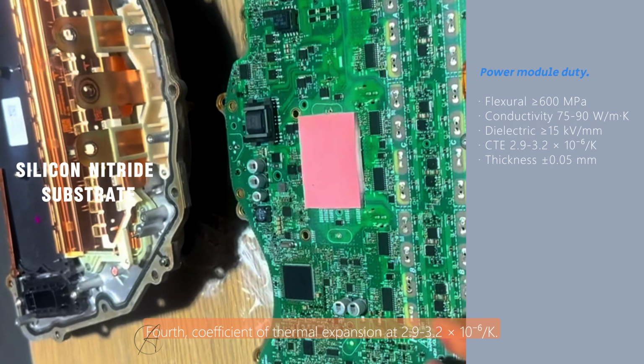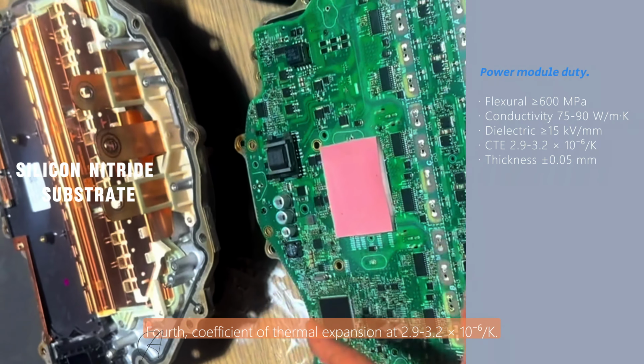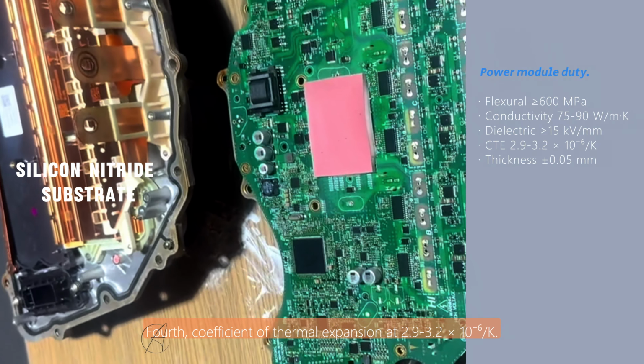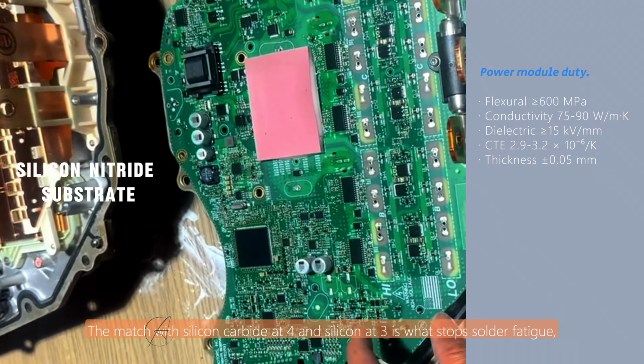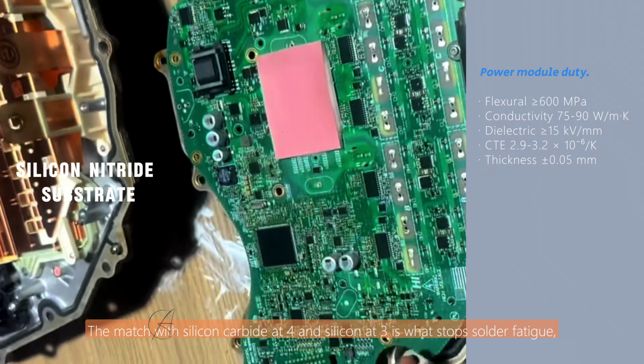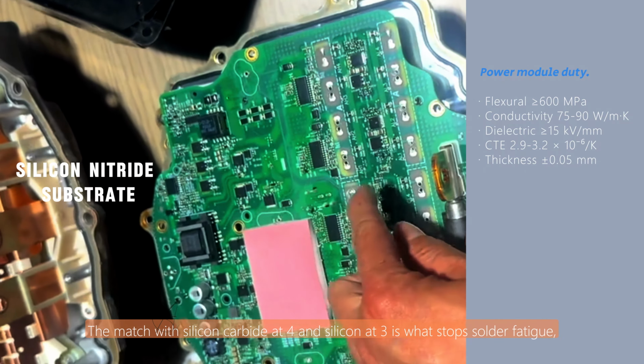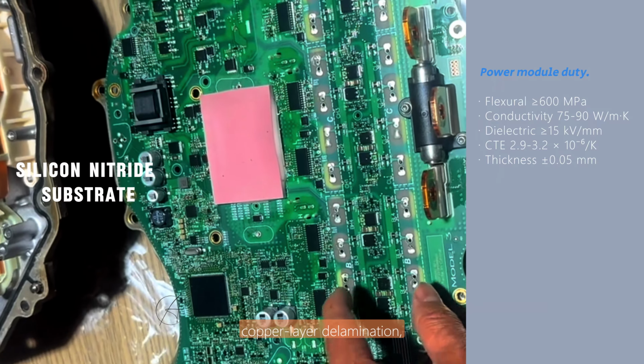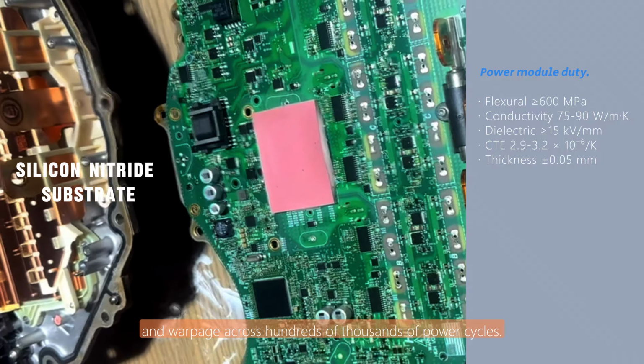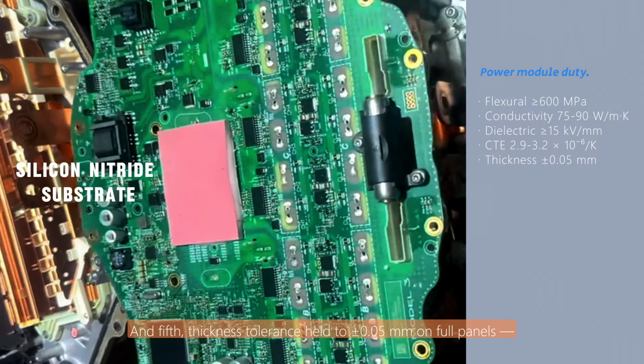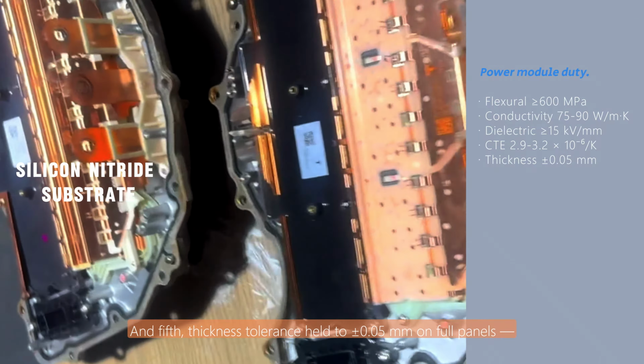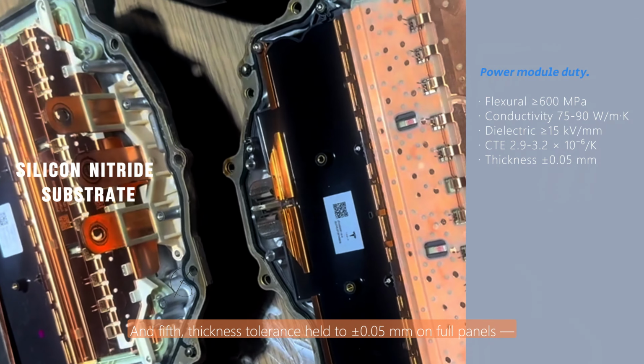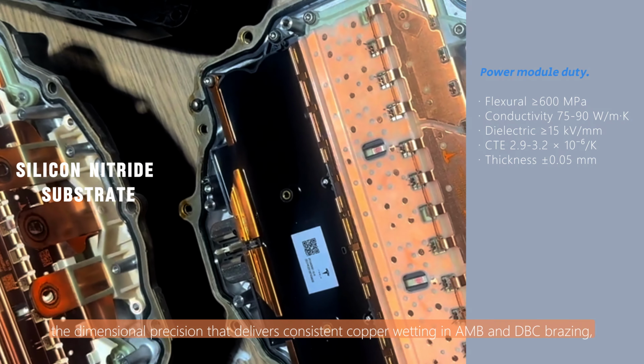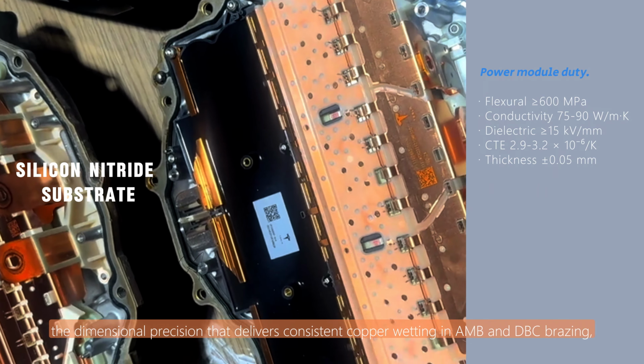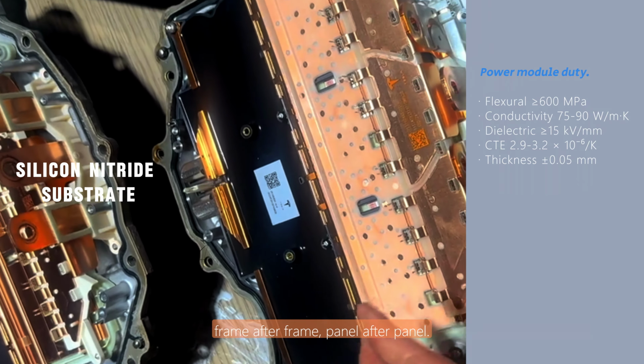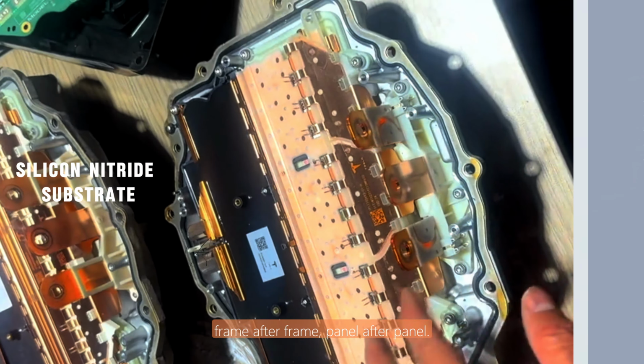Fourth, coefficient of thermal expansion at 2.9 to 3.2 micrometers per meter per Kelvin. The match with silicon carbide at 4 and silicon at 3 is what stops solder fatigue, copper layer delamination, and warpage across hundreds of thousands of power cycles. And fifth, thickness tolerance held to plus or minus 0.05 millimeters on full panels. The dimensional precision that delivers consistent copper wetting in AMB and DBC brazing, frame after frame, panel after panel.